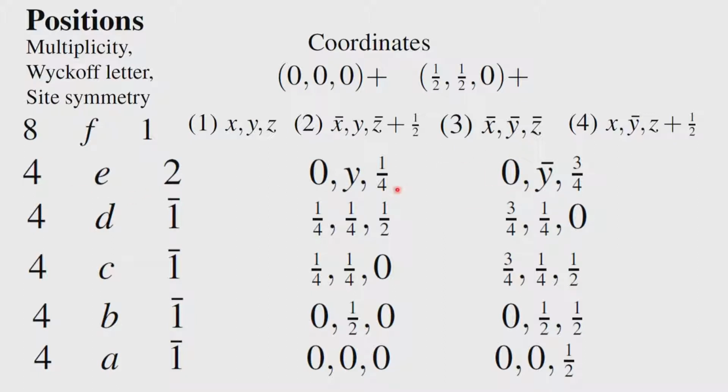So, the presence of the twofold or the 1 bar symmetry, in other words, the molecule now can either possess a center of symmetry or the molecule can possess also a twofold symmetry. If the molecule possesses a twofold symmetry, it will go and sit with respect to the twofold axis, which is now a special position. So, you notice that the Wyckoff notation, the highest symmetry is always with respect to 0 0 0.